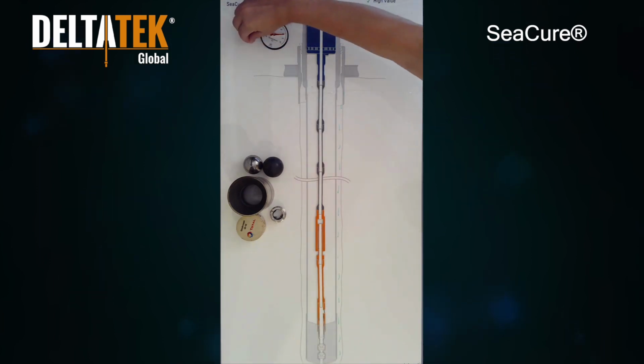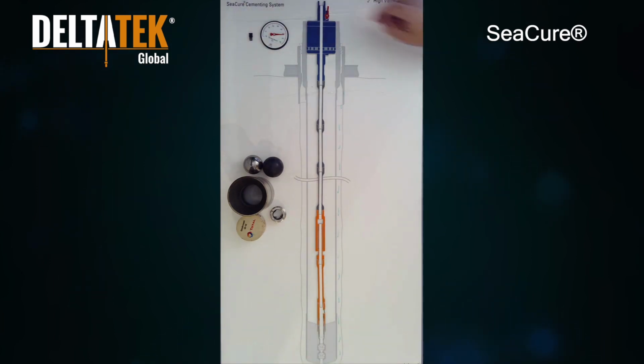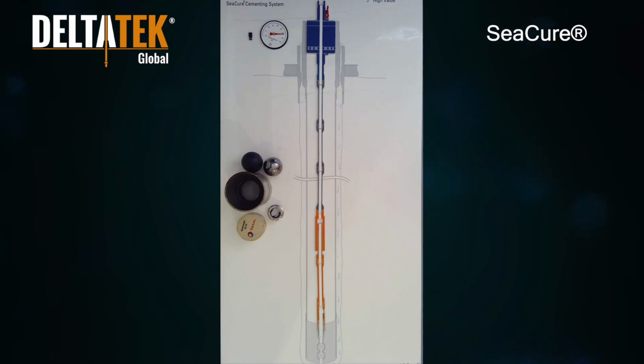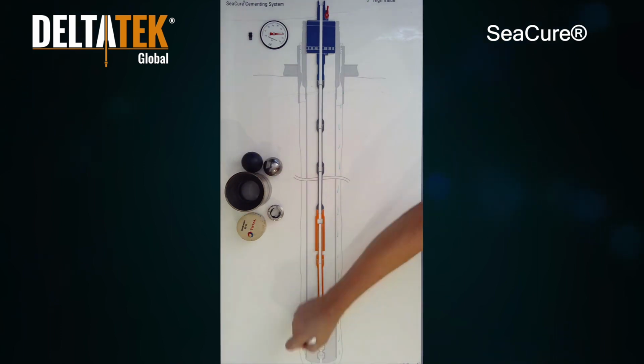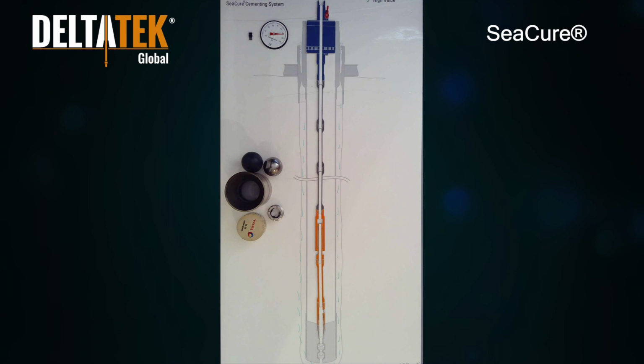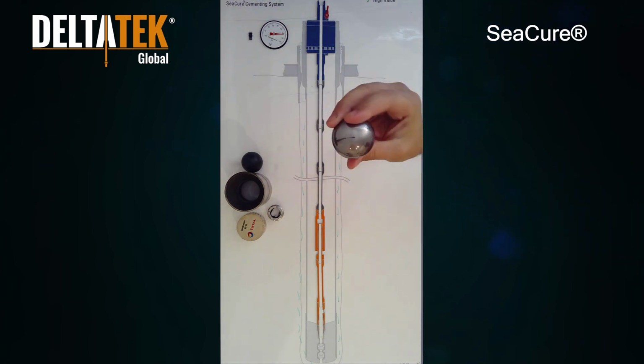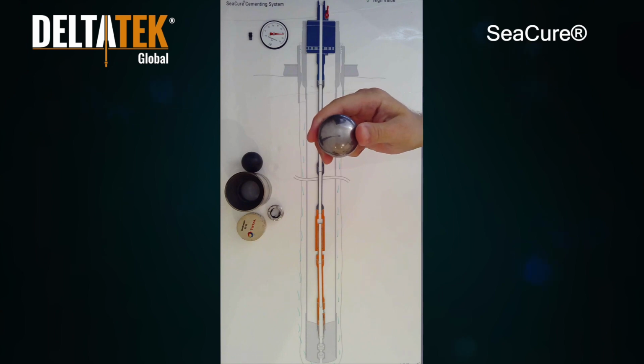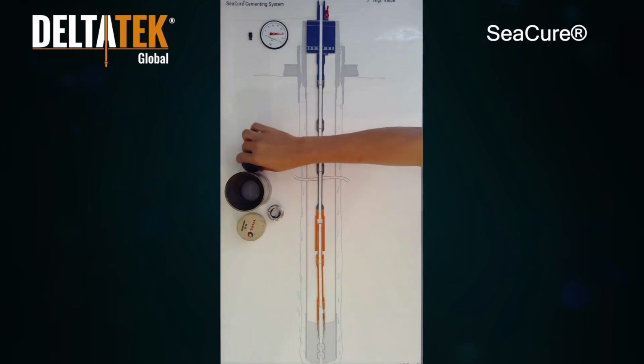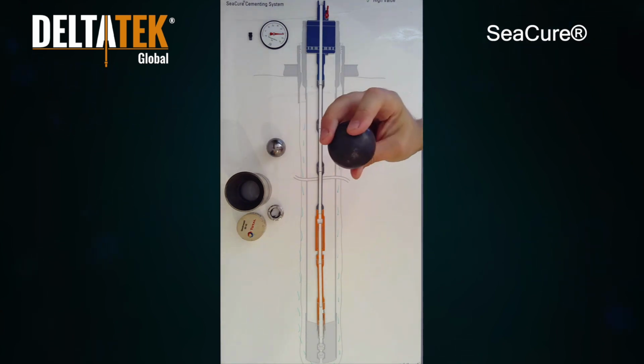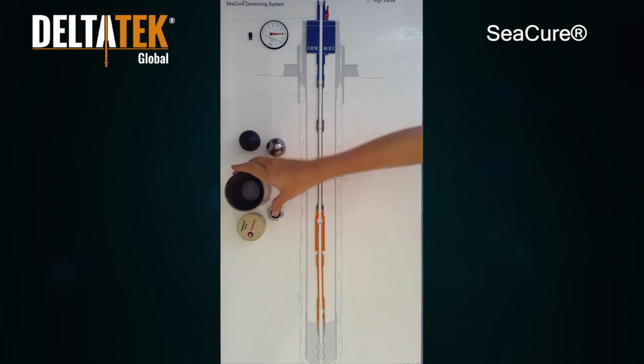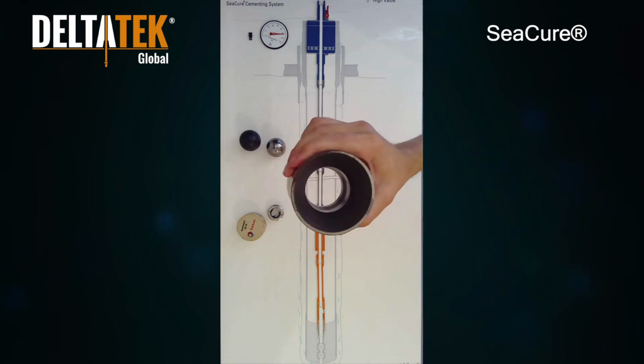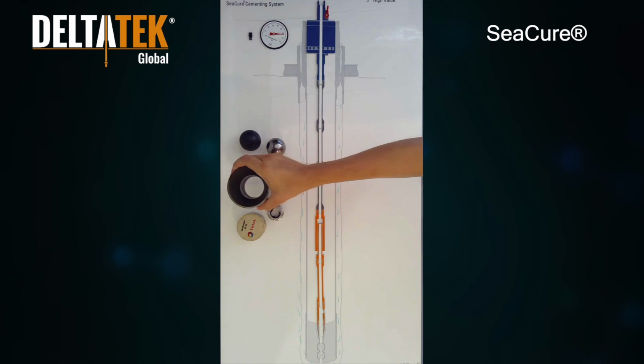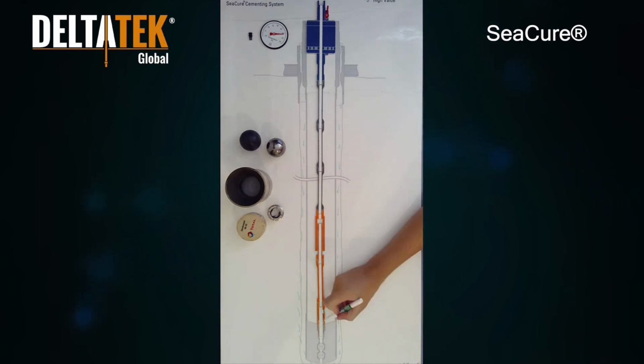Once the primary cement job has been pumped, instead of launching a wiper plug, the SeaCure ball is dropped into the inner string after displacing the cement job within a few barrels of the shoe. The SeaCure ball starts its life as a 1.75 inch tungsten core. It's built up to 1.9 with an NBR coating, seating within a 1.88 counterbore in the ball seat. It's been pre-installed in the latching adapter, roughly 14 inches off the nose.